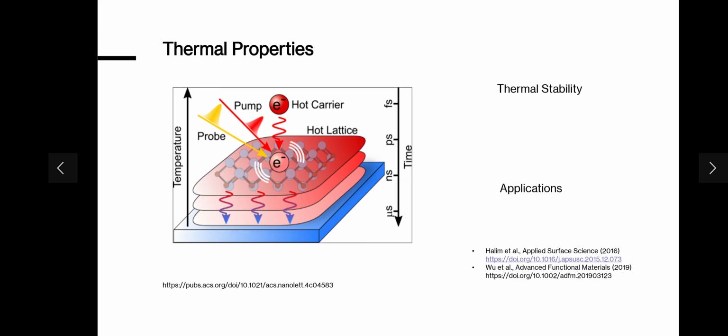Alright, carbide sheets also have very good thermal properties. Their thermal stability is among the best. Most MXenes are thermally stable in an inert atmosphere up to 600 to 800 degrees Celsius, depending on the surface terminations. The decomposition often starts with loss of the hydroxide or fluoride groups around 300 to 500 degrees Celsius. Then the oxidation of the carbide backbone begins at temperatures over 500 degrees Celsius.